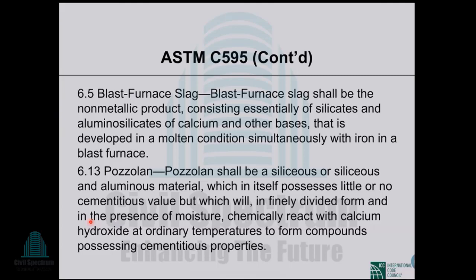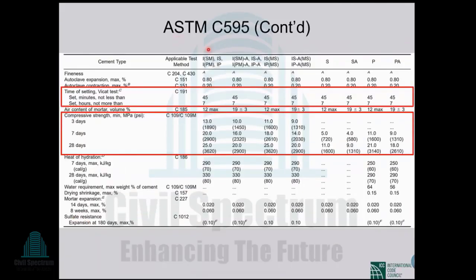So for ASTM C595, we can now compare the standards. In BDS EN, CEM I we have to compare with ASTM C150 type 1, and for CEM II we have to compare with ASTM C595 type IS or IP. So if we compare the properties as mentioned, ASTM C595 and BDS EN CEM II type cement, then we see that here again for setting time, ASTM is providing limits for both initial setting time and final setting time. The initial setting time is 45 minutes, a little bit more strict than EN. In EN standard, for 42.5 strength class, the